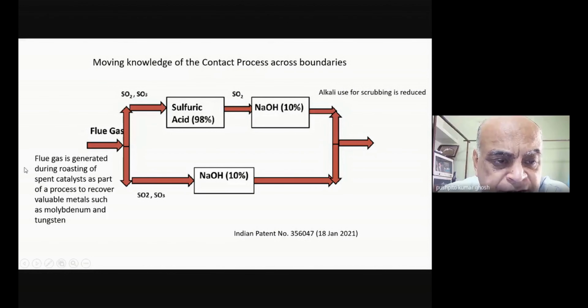What they do is recover metal value from spent petroleum catalysts. One of the processes which they use, the first thing is that they have to roast the spent catalyst to burn off all organics. And then they basically do hydrometallurgy and extract out selectively things like nickel, molybdenum, cobalt, etc. Now, what happened was that when they were doing this, there were a lot of sulfur compounds also in the spent catalyst, so that when they were roasting, their roasting temperature was about 650 degrees or 700, they were generating flue gas with a fairly high amount of SOx, SO2 and SO3.